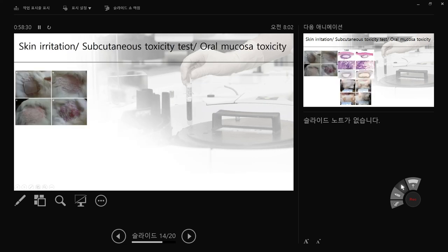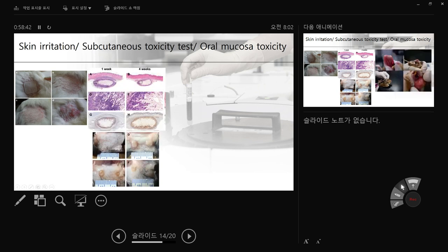For subcutaneous testing: open the skin and place the material in the subcutaneous layer — under the skin but above the muscle. This is the subcutaneous layer. You can check how the material is encapsulated, examine immunogenic and inflammatory responses, and count inflammation cells and blood vessel number. Optical images are used. For oral mucosa toxicity: mice and rats cannot be used, but hamsters have large oral mucosa. You push out the hamster's oral mucosa, put the material in, use a necklace to prevent swallowing, then sacrifice and evaluate histologically.